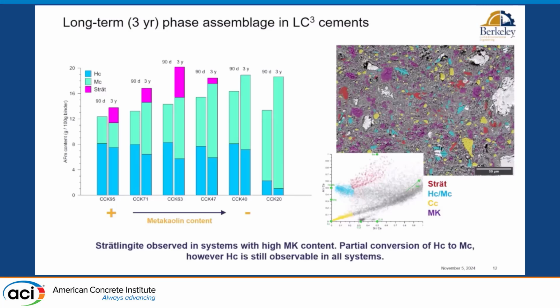But in a sense, and overall, even in the long term, these AFM phases continue to precipitate in the microstructure of LC3. This is an overview of what happens at 3 years. We have some conversion of hemi-carboaluminate into monocarbonate in the long term, but what I want to highlight here is that hemi-carboaluminate is observed in the microstructure even in the long term. So this is a phase that has thermodynamic stability in the long run.